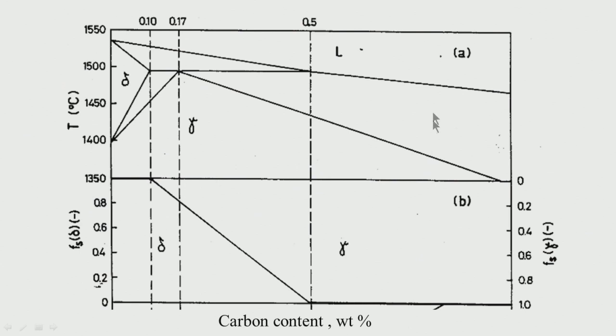And look at the solidifying range, it is quite wide here, while here it is relatively less. So, you can make out that the solidifying temperatures are changing. This is the equilibrium solidus temperature. With segregation, this will become still lower. So, it will become a much wider solidifying temperature range as you go to high levels of carbon. With more segregation, it becomes wider.